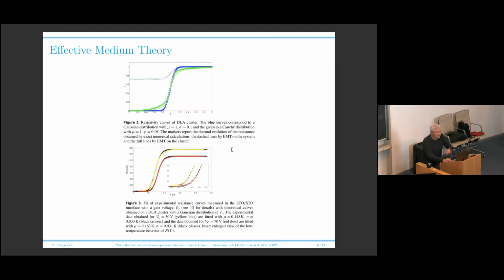So the real numerical solution does percolate, and you see a very nice metal to superconductor transition. Now, this transition has two main characteristics of the real transition observed in experiment. These very long tails, you see here a magnification of the tails. The dots are the experimental data, and the red and yellow curves were obtained by numerical solution of the random resistor network with a fractal structure or a pseudo-fractal structure of the superconducting cluster. And this produces very long tails because you have to populate your fractal before percolating. But on a fractal, you can percolate with a superconducting fraction, which is much less than the percolation threshold in two dimensions with totally random disorder.